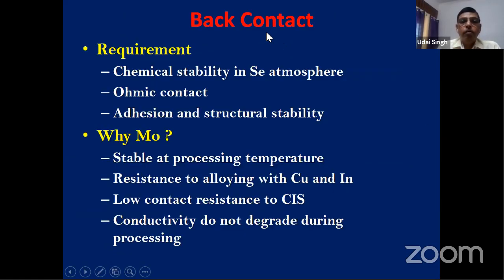So, back contact. First, what we will see is what the requirements are. It should be chemically stable in the selenium atmosphere, because you're trying to selenize it. It should give a good ohmic contact. If it's not a good ohmic contact, it is highly resistive. And then adhesion and the structure. Adhesion is also very important, because it should not happen that after a few days the film comes off. So adhesion is also a very big parameter.